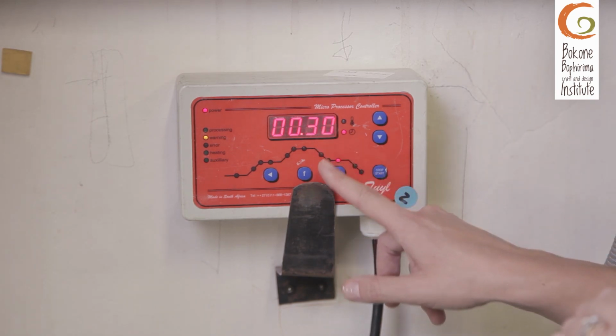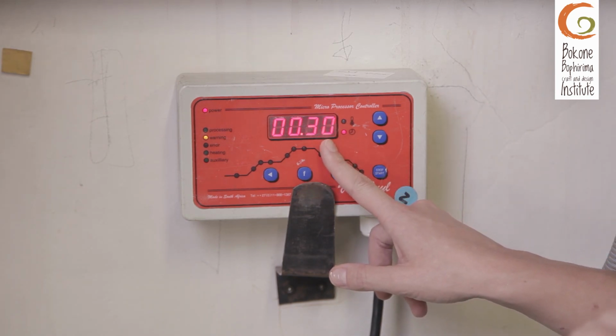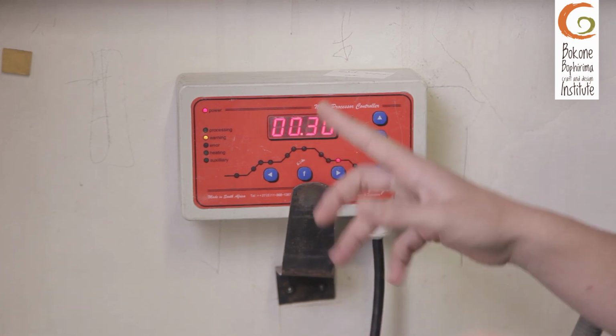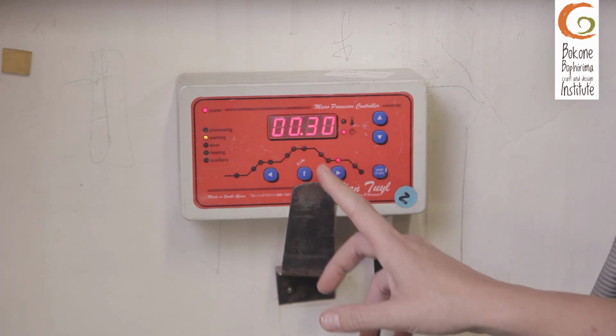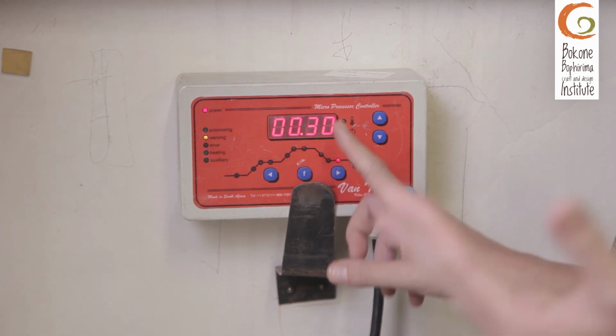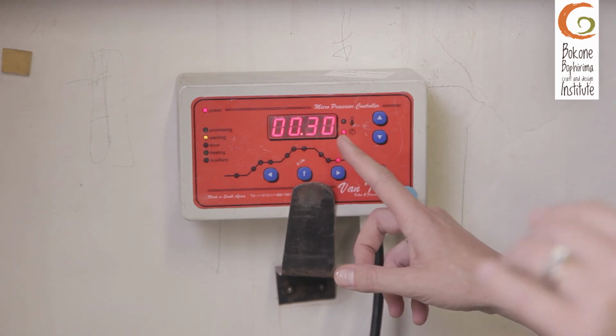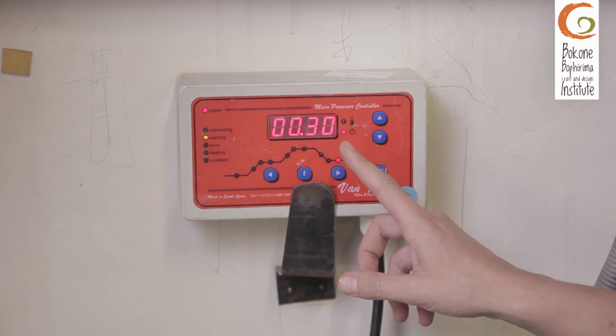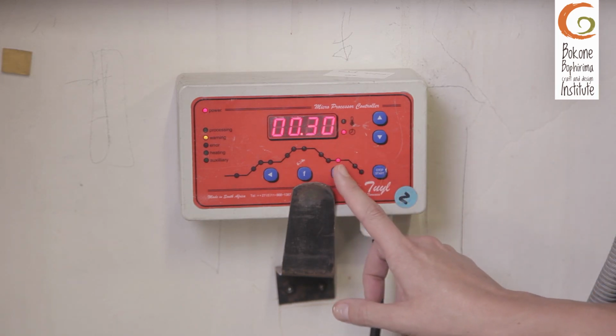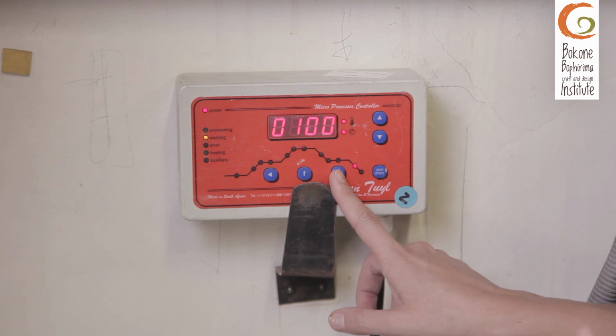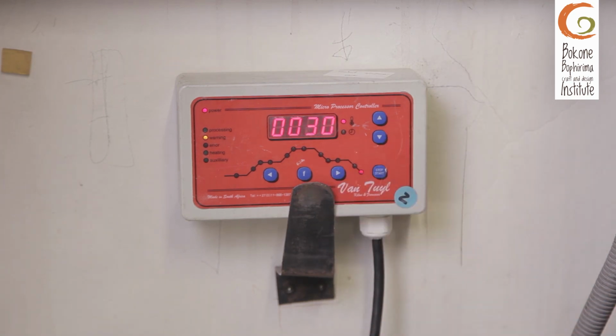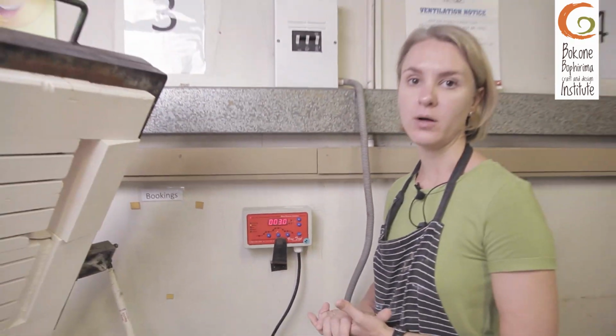I like to hold it for a longer period at 580 when slumping, because our glass and our mold will cool at different temperatures. It's important when we get to 580 to ensure that both are 580 before moving down slowly when we are going to anneal. I'm then going to anneal for 100 degrees an hour down to 30 degrees or room temperature when we can open the kiln lid.